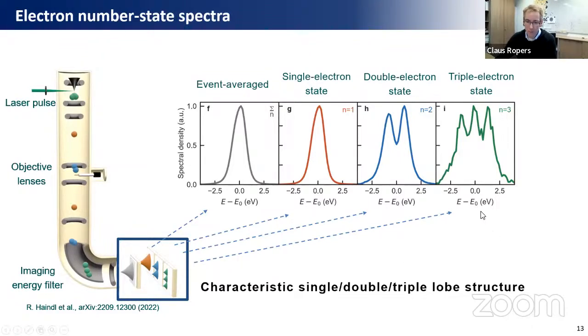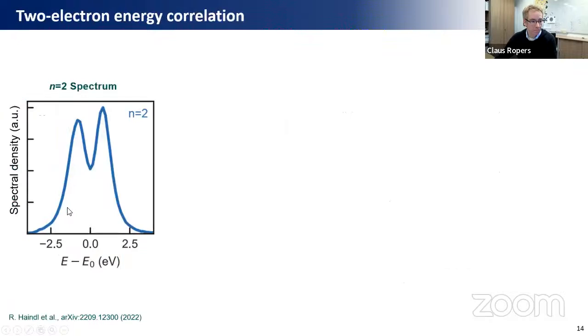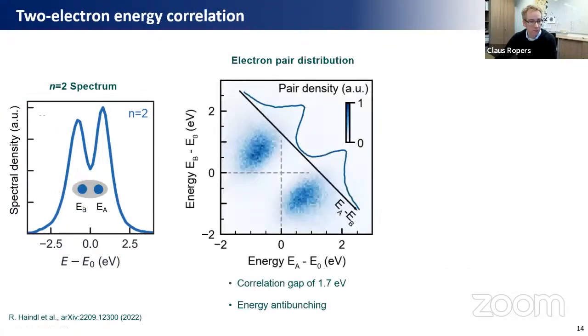And then thirdly, if we only plot the electron spectra that arise from the 3 electron events, so those laser pulses which have produced 3 electrons, you get a very well-defined 3-lobed structure here, which is also not exactly expected from the source, because it's actually a larger source than what you would guess from having such strong interactions. Okay, but let's look a little bit closer at the distribution of these electron energies. So as I said, we can record the electron energy for each of the laser pulses and for each of the electrons in each laser pulse.